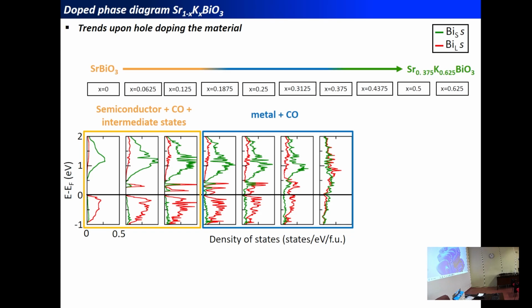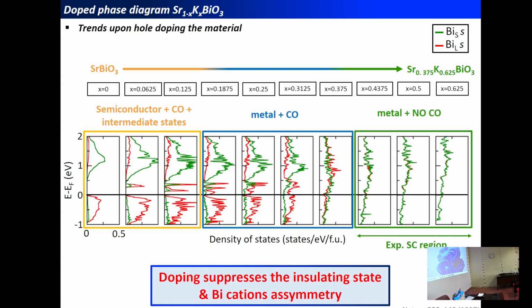And with this type of charge ordering, we can see the asymmetry of the density of states up to 37.5% of substitution. And if we go beyond this threshold, we end up with densities of states which are very similar. There is very likely no more charge ordering in the material, and therefore we can conclude that in this system the doping is suppressing the insulating character of the material in agreement with experiment, but also it's removing the bismuth cation asymmetry that we have at the beginning in the material.